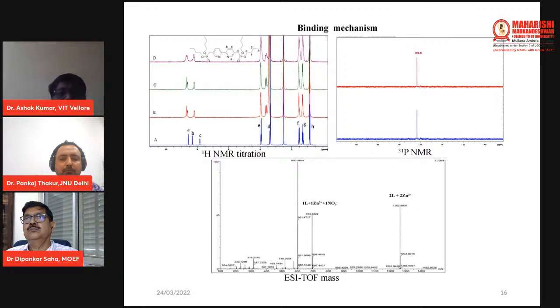Using this particular experimental proof, we can make an assessment that with the zinc, the coordinating sites are nitrogen. With the thorium, the coordinating sites are phosphoryl through the side arms. So in this way, this particular molecule worked out.